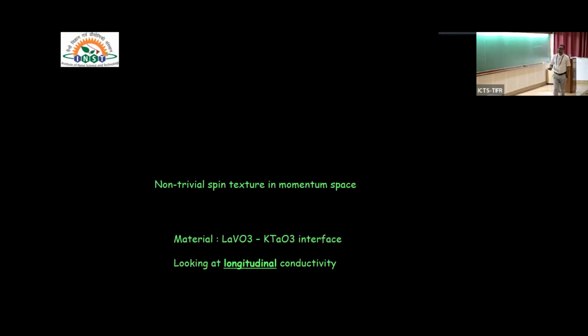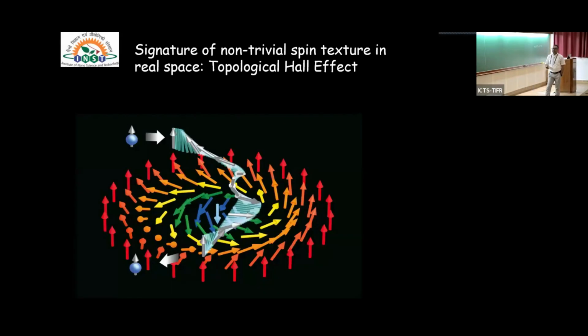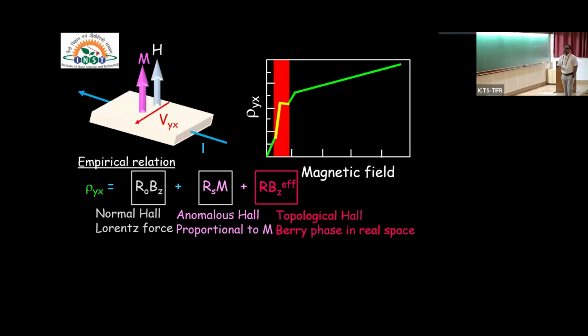Now, in the second part, which is the non-trivial spin texture in momentum space, we're going to talk about the lanthanum vanadate potassium tantalate interface and look into the longitudinal conductivity. If you have a non-trivial skyrmionic spin texture in real space and you send an electron through this, what happens is the following. In a normal material, if you look at the Hall measurement with no magnetization in the system, the normal Hall comes from the Lorentz force and is simply proportional to the applied magnetic field. In a magnetic system, in addition you have a term proportional to the magnetization of the system.